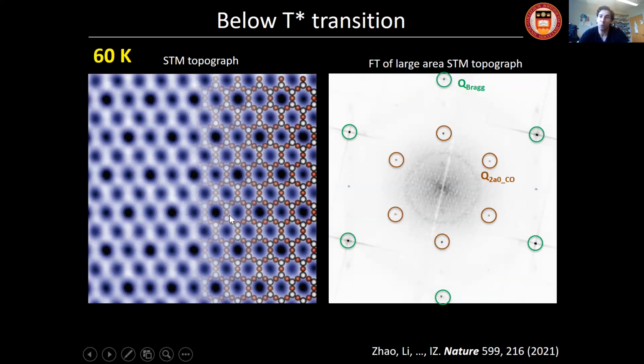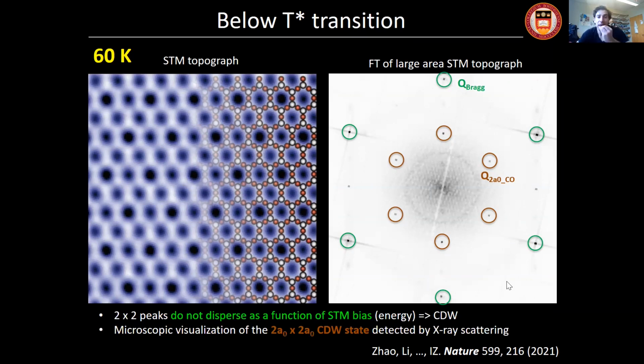And if you want to convince yourself by eye, what does this correspond to in real space? Well, you can see maybe this is darker, brighter, darker, brighter. So there's a staggered intensity pattern in the topograph itself. So this is again a 2x2 charge density wave visualization from STM that we can see at 60 Kelvin. This should persist to about 80 to 90 Kelvin. In CsV3Sb5, it's about 94 Kelvin, I think.